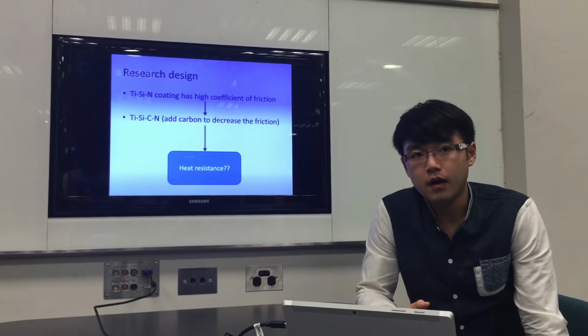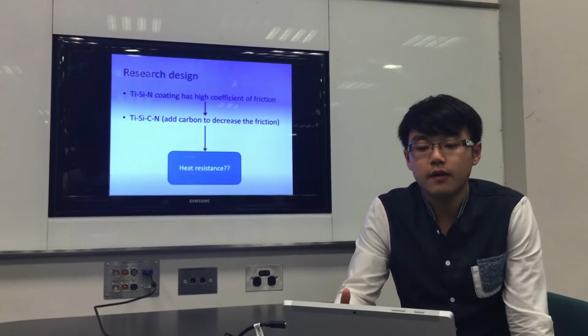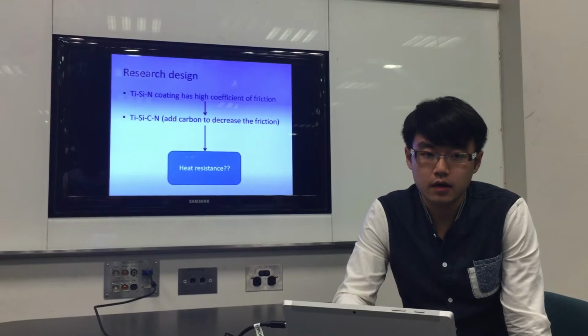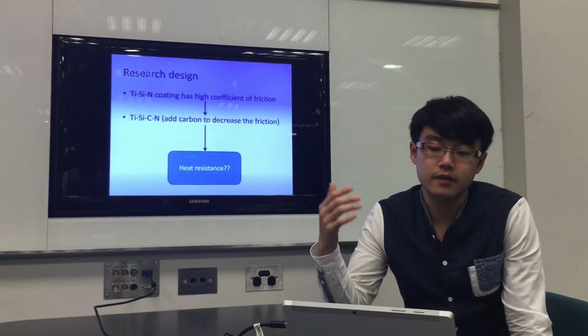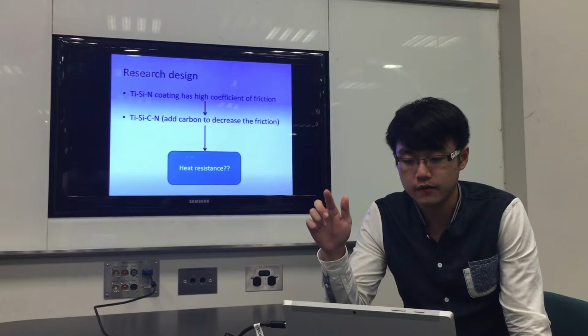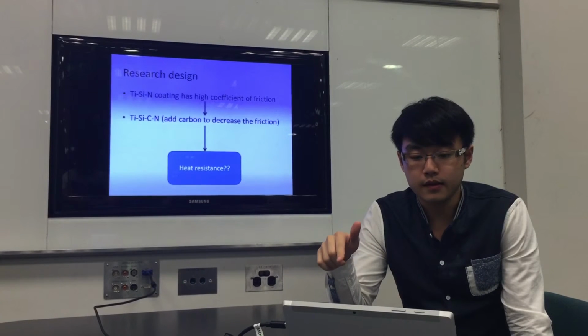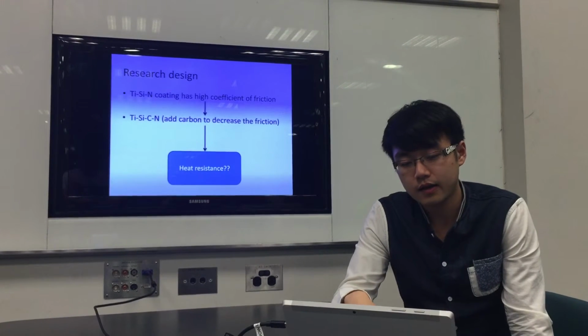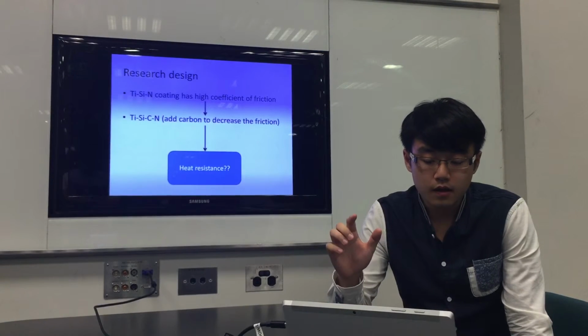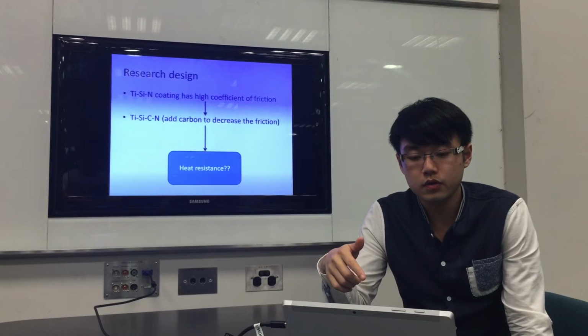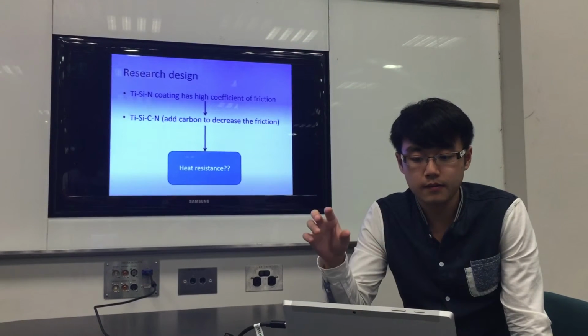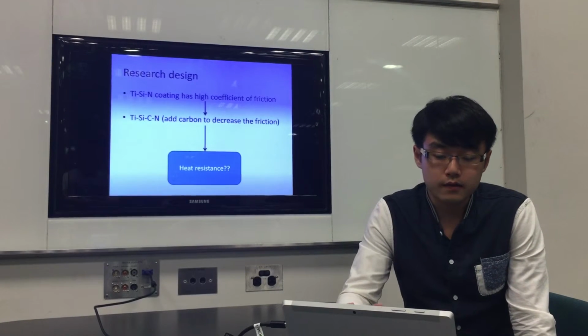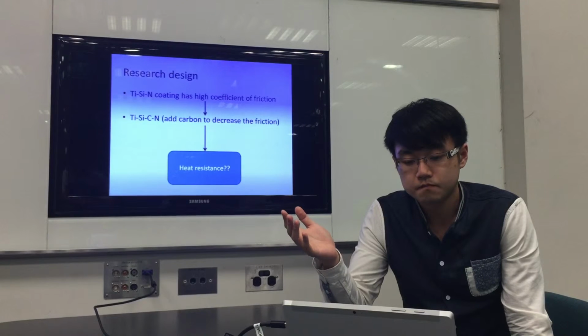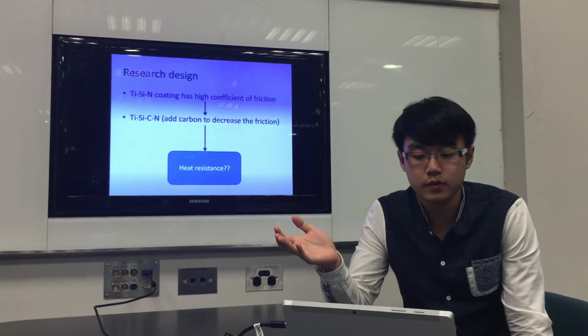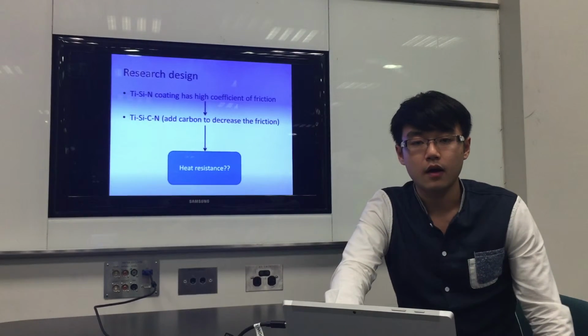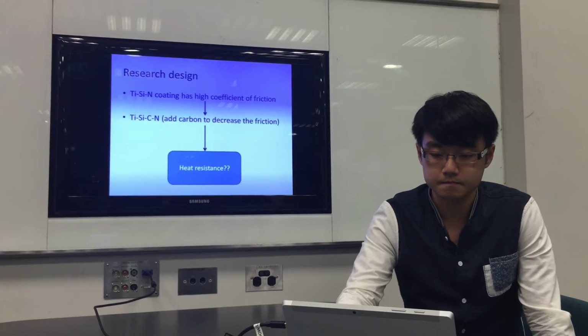Okay, next part, I will introduce the research method. In this research, I found that the titanium, silicon, and nitrogen coating has a high coefficient of friction. So we add carbon into this system, the titanium, silicon, carbon, and nitrogen system. When we put carbon into this system, it can decrease the friction. But until now, we found that no one has introduced the heat resistance of this system. So I made a design for this system.